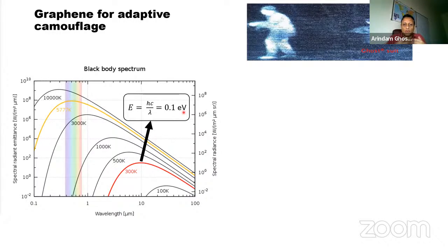Now, what happens is that when we wear clothing, these photons continuously get absorbed by our clothing, and then it gets re-emitted. And when we are even in the dark, a thermal camera can actually record these 100 milli electron volt energies, and they can image us. And you can see the image here is essentially a soldier who has been imaged in the night vision camera or infrared camera, which can record these kind of radiations at 10 micrometer wavelength.